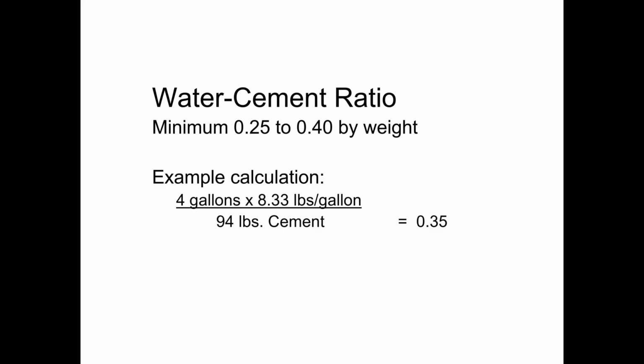So given that we are going to be losing some moisture, generally we want to have a water cement ratio that is a little bit above 0.25 as our starting place. So even with zero slump mixes like those used with Hollowcore, oftentimes we see a water cement ratio in the 0.28 to 0.31 range. So even for a zero slump mix, we're going to have a water cement ratio greater than 0.25.